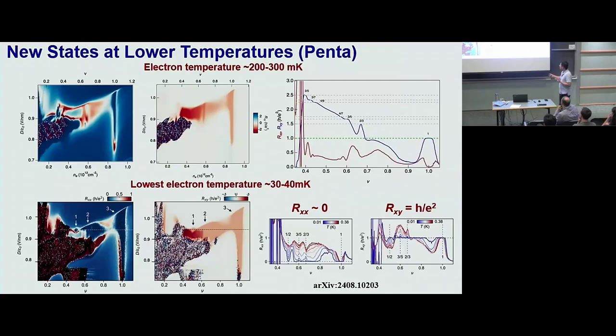Experimentally, we know that now if you do a line cut like this along the dashed line, you find that these 3 regions almost connect into one, that the Rxx touches 0. At the same time, Rxy seems to develop a big plateau here at h over e squared, an integer value, even at fractional filling factors like 3/5 and 2/3, if you cut here. Okay? So something is going on at the low temperature.